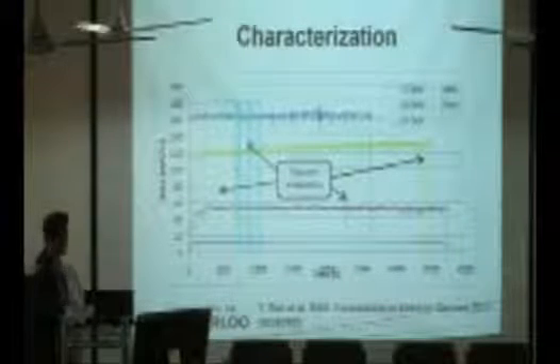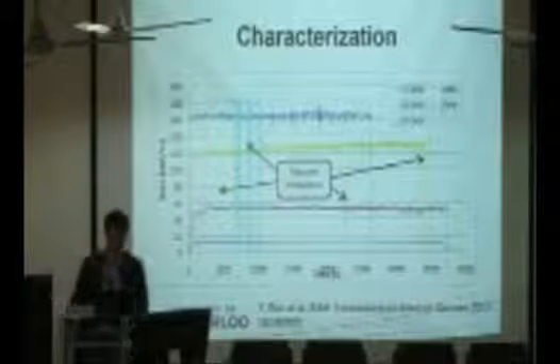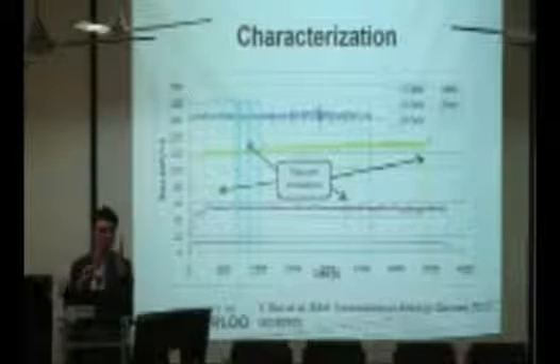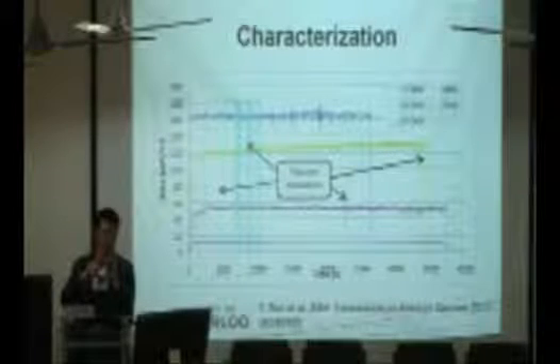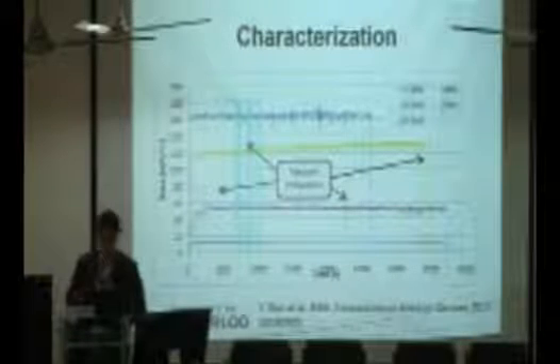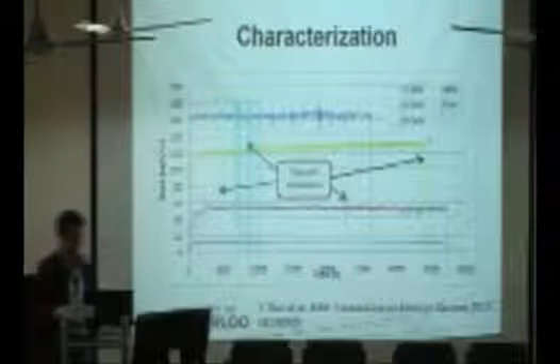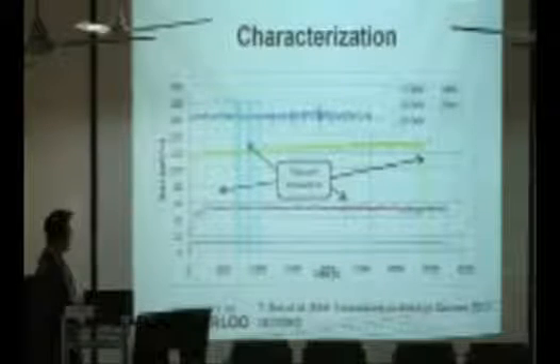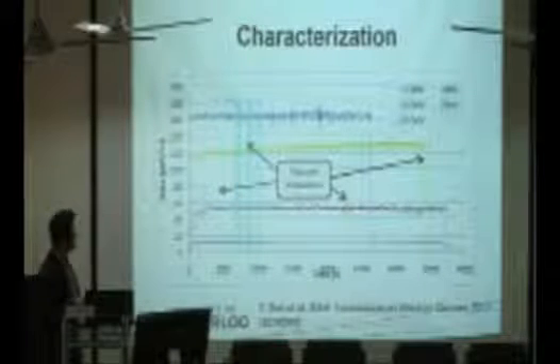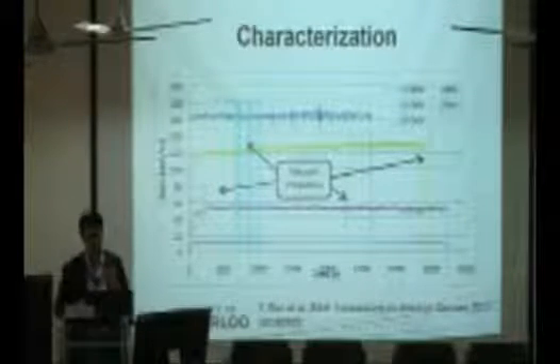And you could see instability here. The instability is caused by the outgassing of carbon nanotube. So at this point, carbon nanotube is still burning off. As it burns off, it's releasing carbon material into the vacuum chamber, and that would degrade the quality of the X-ray. But we're confident that at the level of 25 kilovolt, we can create really stable X-rays.